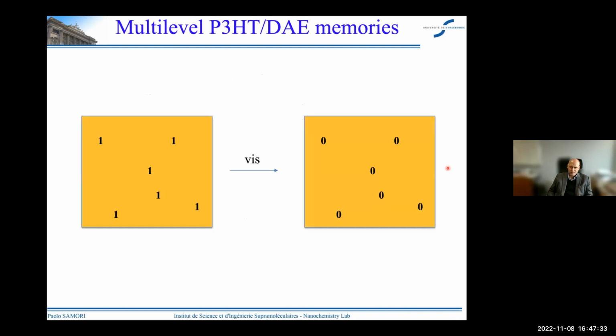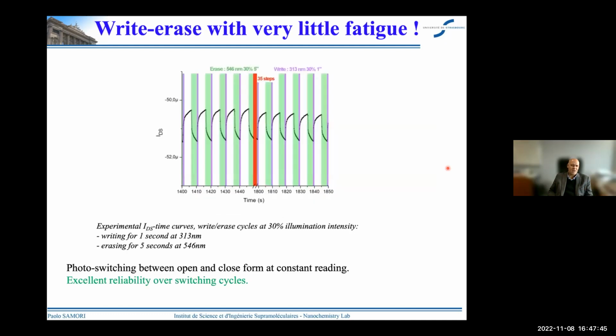Now, of course, if you have a USB key, if you have your hard disk, you want to use it more than once, so you need to be able to write and erase. And here the erasing can be done by illuminating with visible light. And you can make cycles, you can see here with writing and erasing with a very, very high precision, no fatigue at all. And so that gives high reliability over the switching cycles.